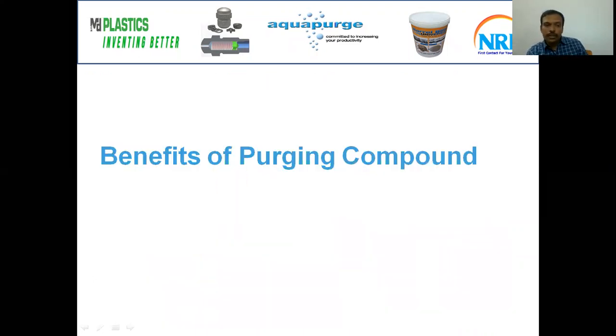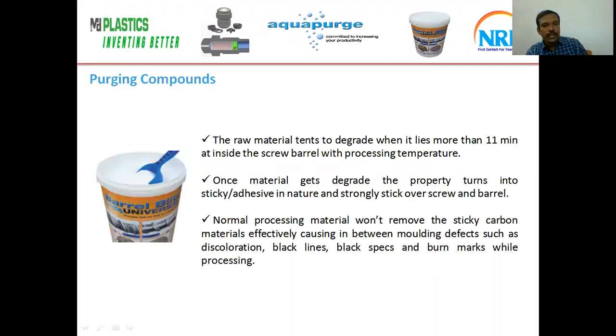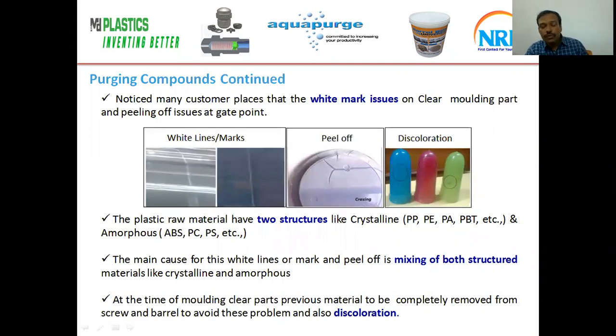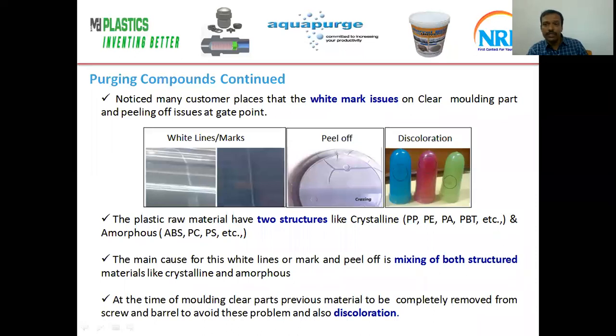Next, I am going to talk about the benefits of purging compound. See, normally any plastic material tends to degrade if it lies more than 11 minutes inside the screw barrel at processing temperature. Once the material degrades, it becomes sticky or adhesive in nature. Once it sticks on the screw and barrel, it is very difficult to remove. Normally processing materials won't remove the carbon effectively, so it causes black dots or black lines during molding. So we have to use purging compounds to remove the carbon and eliminate these defects while molding.